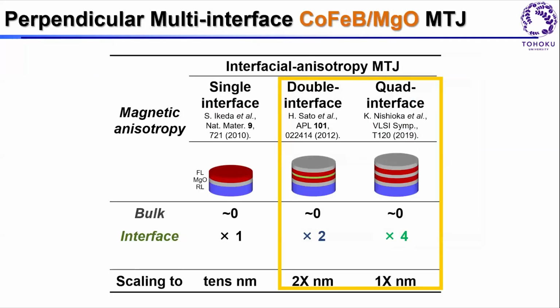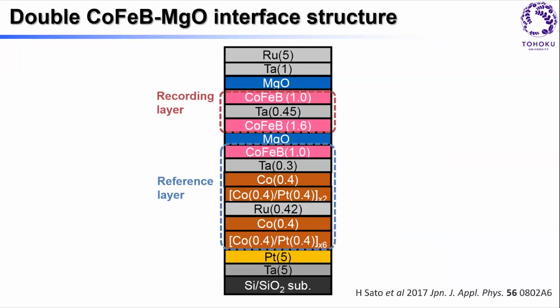Okay, so that's how we got a single interface. We can have two interfaces. Remember that the interface is a source of barrier height. So if you have two interfaces, we can increase the barrier height by 2 times. And if you make it 4, then 4 times as well.